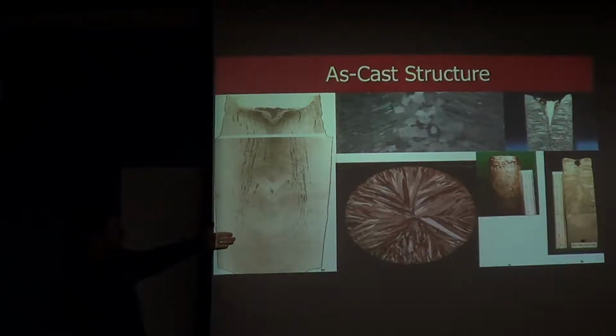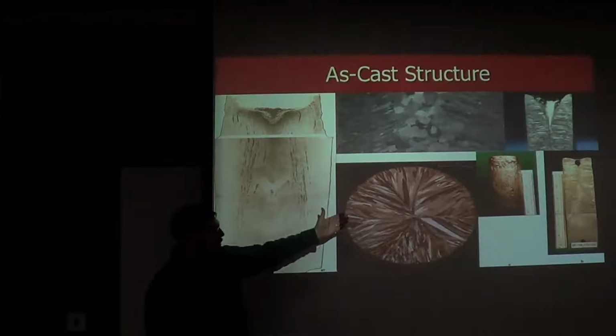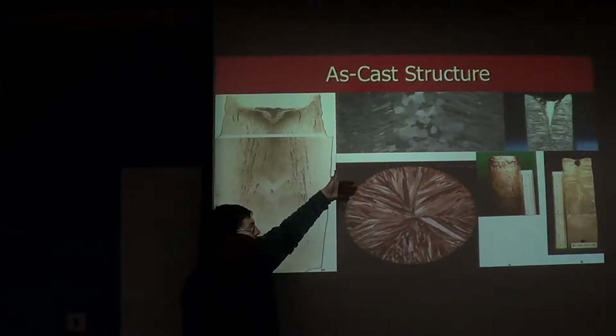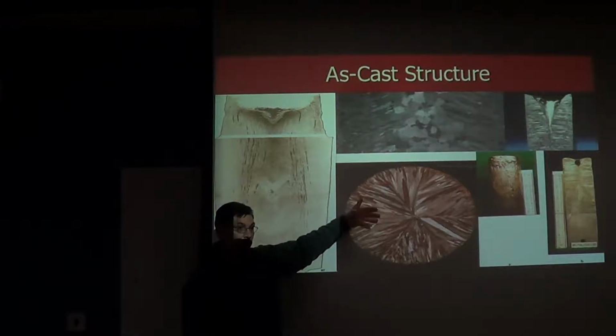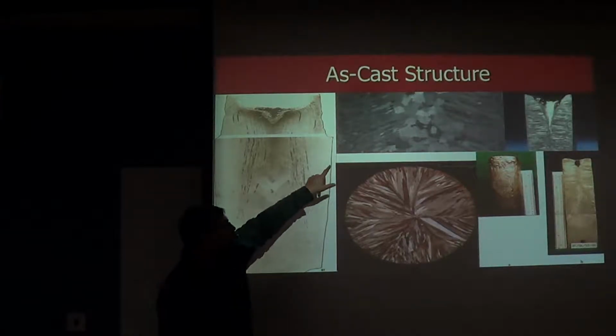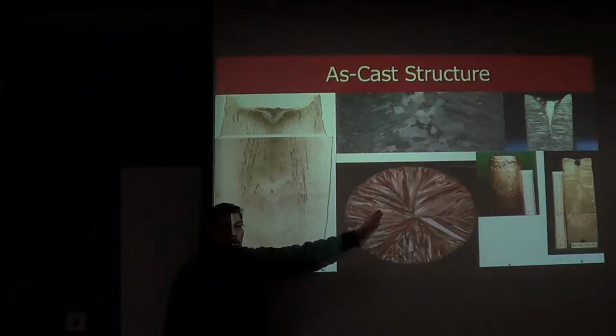Good. Okay, so I think we touched a little bit on this last week, but here's that cross-section showing the segregation in the macro-etch. This is the ingot split from the top to the bottom. Here's a radial cross-section, or a transverse cross-section. You can see the columnar orientation of the grains, right? And we can see other structures in these, here we've got equiax and columnar together. That's another longitudinal section. So these are showing the as-cast structures.